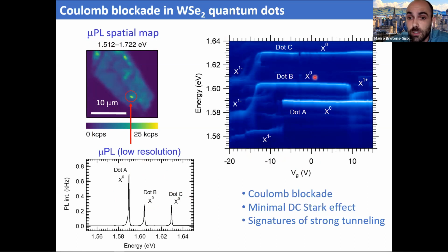And also for dot B, we were able to increase the voltage gate and have tunneling of an additional hole, and have for the first time a positive trion in this quantum dot. So obviously we were very excited about these results, because for the first time we were able to control the charge state in our quantum dots in this tungsten selenide. But on top of that, we observed a few things that were quite interesting.